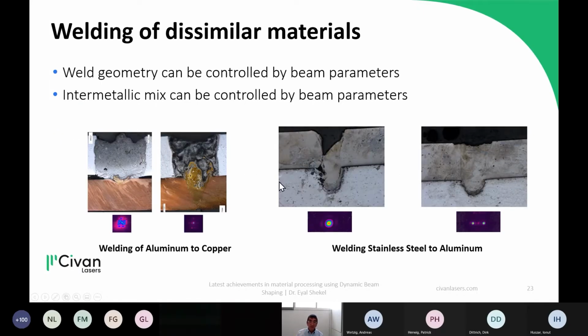Another thing that we investigated is welding of dissimilar materials. So for example, we have here aluminum welded to copper, and here we have aluminum welded to stainless steel. And clearly you can see that by changing the beam shape, you get different results. You can control both the geometry and the amount of intermetallic mixing between the two dissimilar materials.